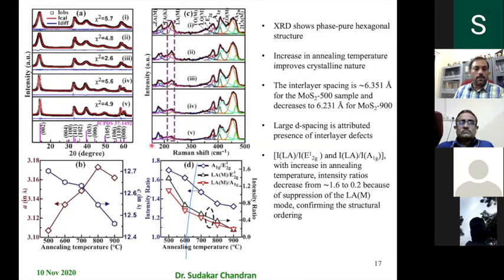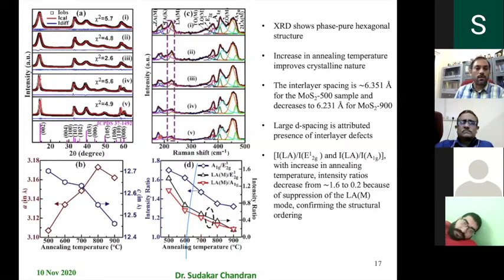The defects, for example, as shown here, the 500 annealed one is very broad, which means the crystallite thickness is very, very small. And then as you increase the temperature, it becomes very sharp. So the thickness increases. Also, the defects in the nanosheets get altered. Raman spectroscopy also can be used to show how the defects in these MoS2 nanosheets change.